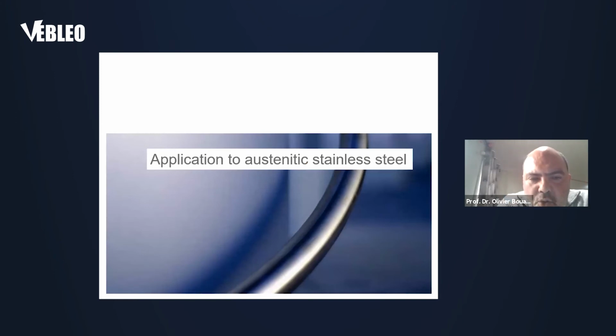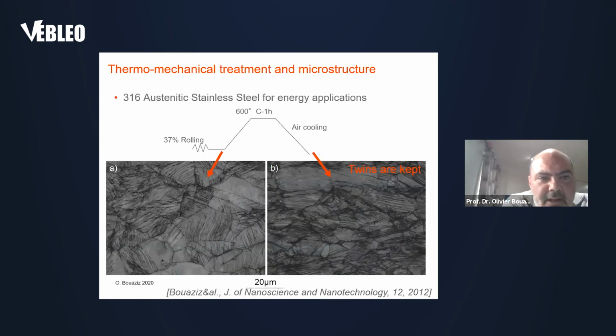So when we saw the promising results of this metallurgical route applied to steel, we have applied the route to austenitic stainless steel. It's a wide market, of course, and it's a currently developed alloy. So we have worked on the 316 austenitic stainless steel for energy application. We have applied 37% of rolling and a recovery treatment of 1 hour at 600 degrees Celsius followed by air cooling.